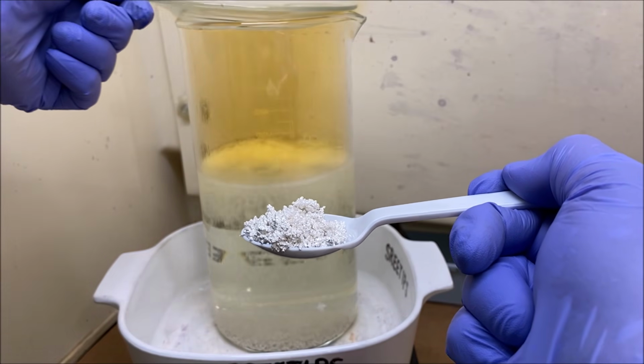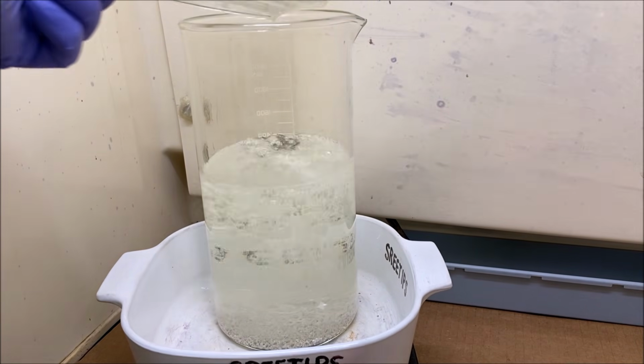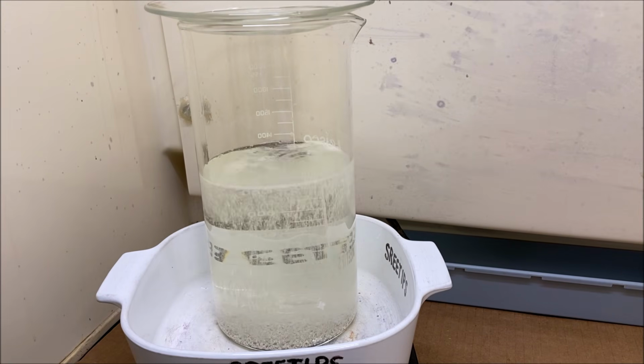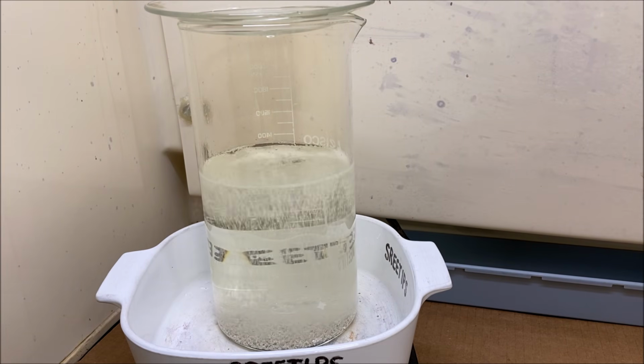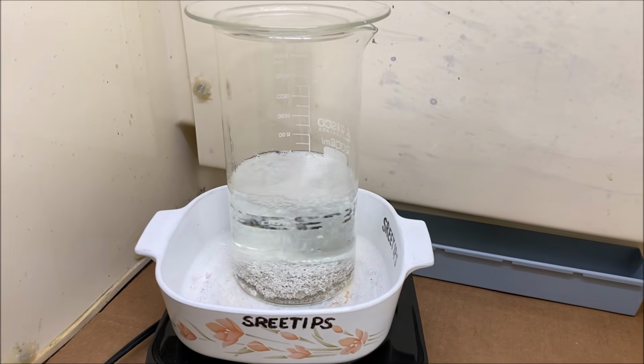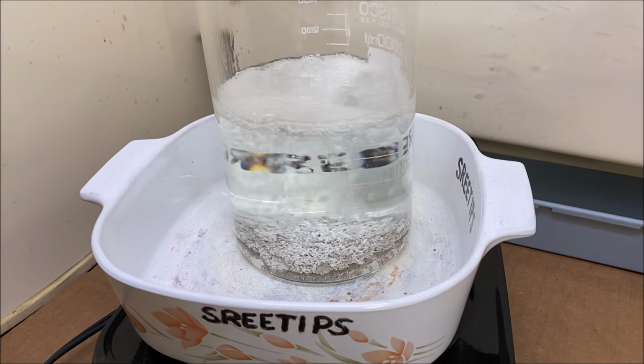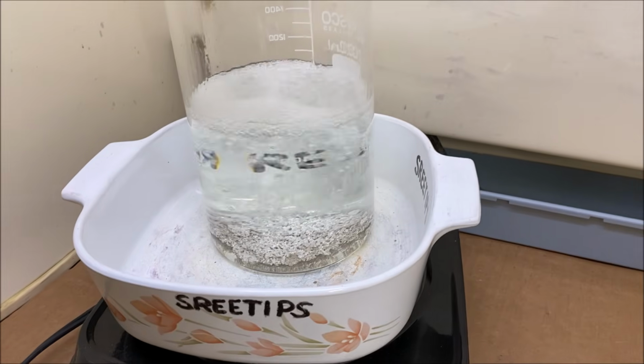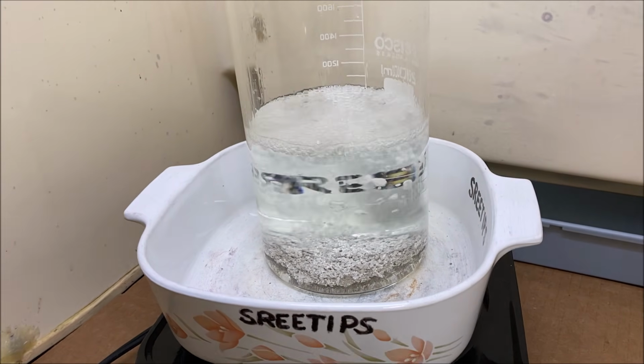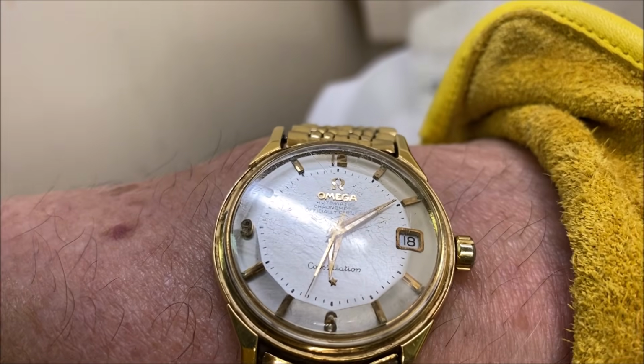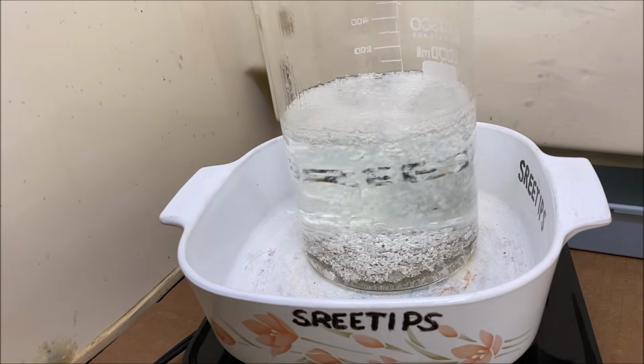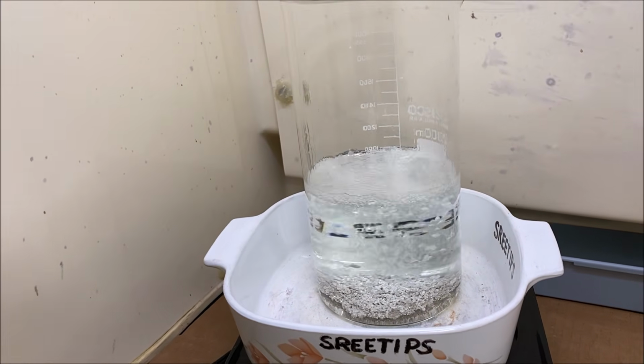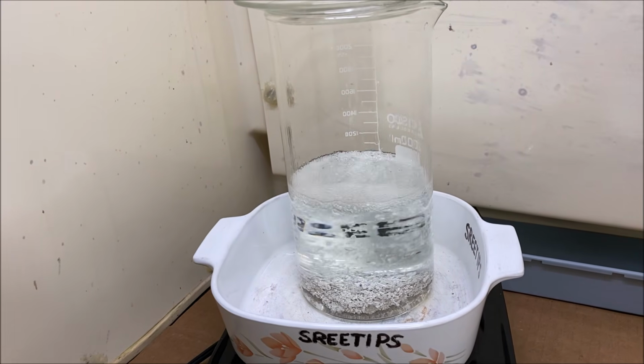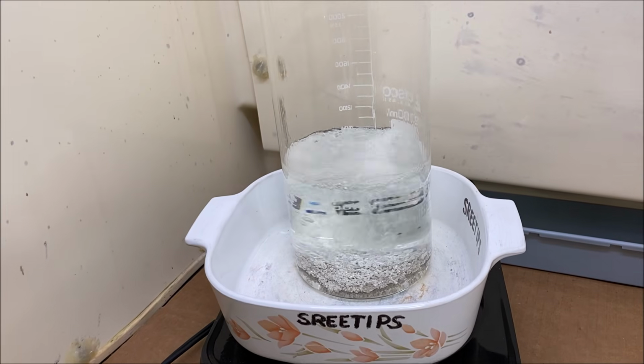I'm adding another spoon of silver in here just to make sure that we've got enough silver in there to completely consume all of the free nitric acid in that beaker. This is perfect. No more fumes. A little bit of silver left down in the bottom of the beaker, which means we've consumed all the available free nitric in there. The time right now is 6:10. We started this about noon, so it's taken about 6 hours to complete this process. We'll use this as the electrolyte for the silver cell.